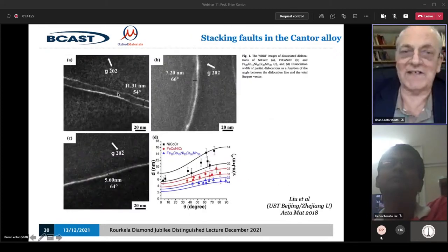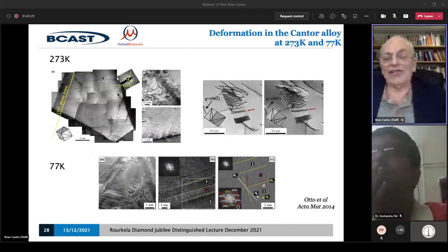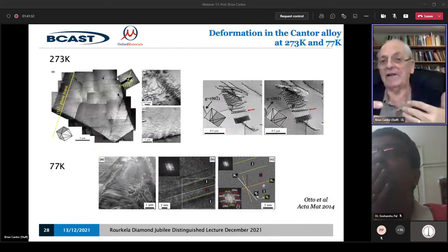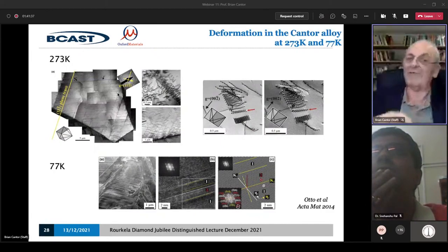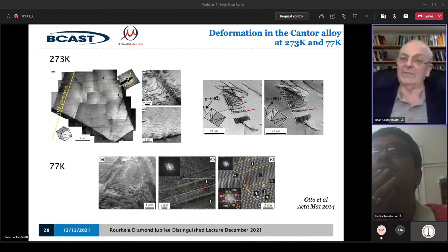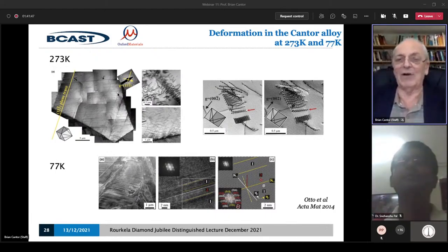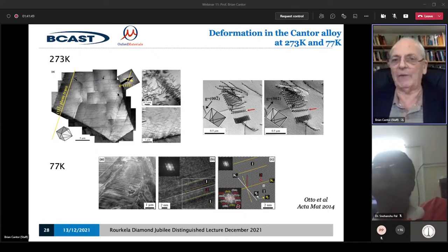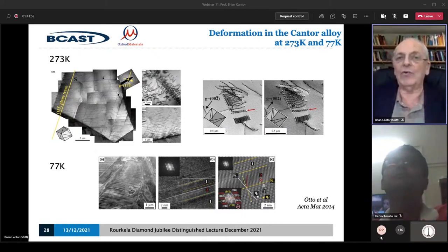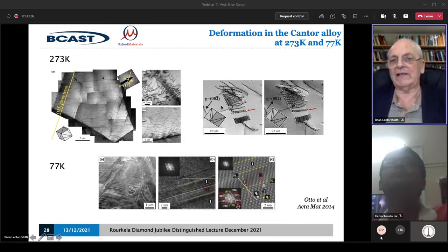The stacking fault energy is variable even in a given material, in a multi-component system, because of the variation of energy and properties from point to point, as I've already mentioned. The diffusion is variable because of that, the vacancy motion, the dislocation motion itself is variable because of that, and also the stacking fault energy is variable because of that. Also, the stacking fault energy is very important because it's very similar to the twin energy.